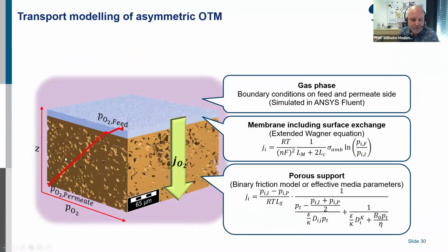That means we have to work also here on a low tortuosity. We have to work on pore sizes in the range of several micrometers. And also we have to develop a thin support. And it depends on the material which layer here is the limiting step for the transport. That can be the support, that can be the surface reactions, but it can also be the material or the thickness of the membrane.